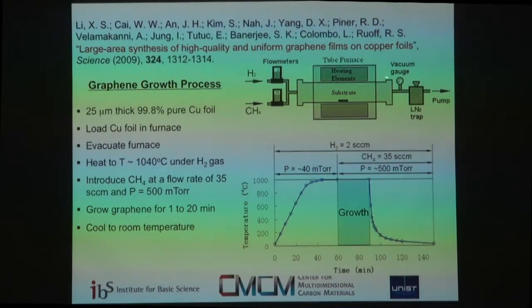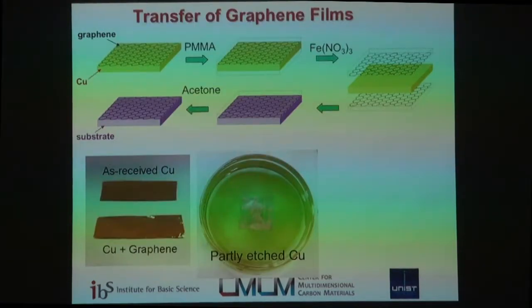So since our work was published, and quite appropriately, people have gotten away from methane in many studies. They've been looking at many other precursors, including halogenated precursors like hexabromobenzene that can form good graphene at 200 degrees C, and so on. I think all of that is incredibly important. Methane is the most stable hydrocarbon. That's why we need a very high temperature to get the growth to occur well on copper, as it turns out.